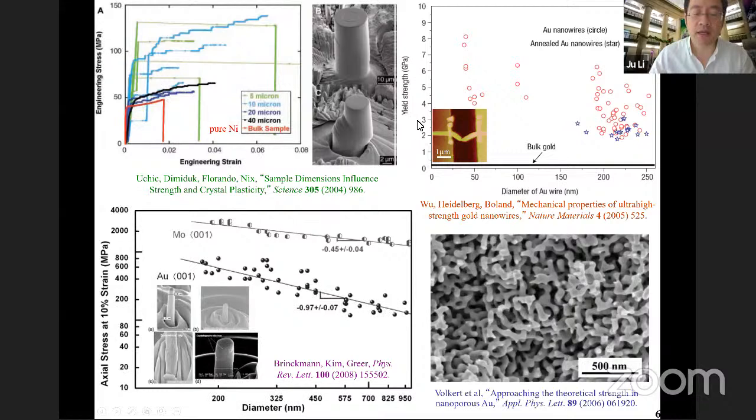In a bulk material, you always have dislocation sources like the Frank-Read source. So what you need is to propagate, and dislocations breed when they move. So all you need is for them to overcome those obstacles. And so it's a mobility controlled strength. But in these pillars, actually the Frank-Read source is not so stable, right?